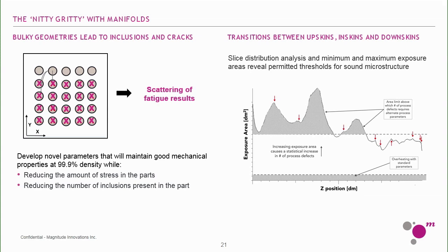And volume jumps on the surface are not a big deal, no pun intended, sorry, because we can post-machine those geometries. But when we have something like a hydraulic manifold, you can't machine the insides. And the answer isn't easy in the sense of just doing extrude hone or some kind of polishing, because you still have to verify all those surfaces. So what we do is focus on smoothing out those peaks by doing some clever exposure strategies.